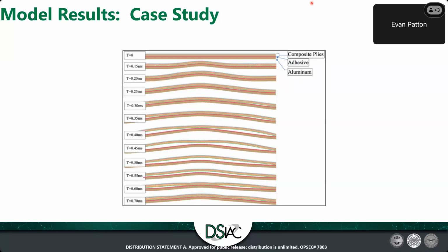This figure here indicates a cross section of that hybrid panel. The brown is an aluminum face sheet, and the multicolored areas is adhesive and composite plies. And this is just a time progression to kind of show the extent of the delamination. You'll see that it begins with an area of high localization deformation that gradually tapers out.